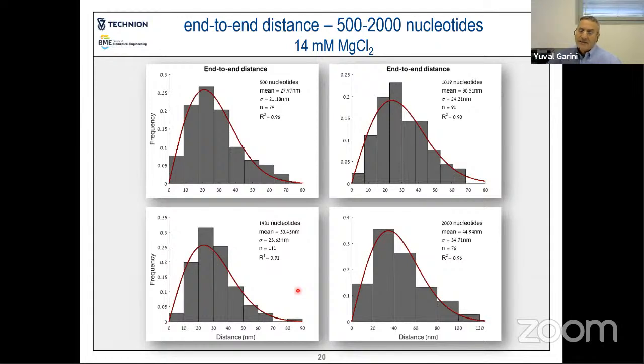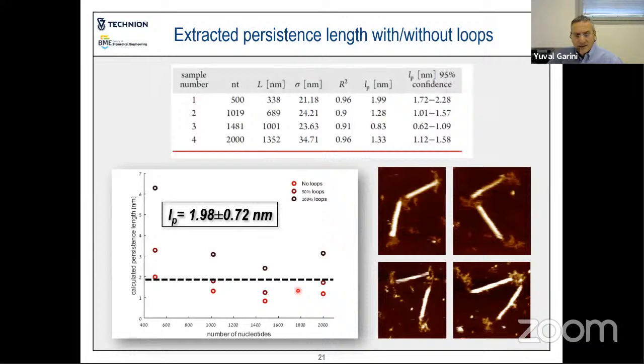We repeated that calculation and fit after assuming that the total number of stem loops is different. And you can see in this summary the results. So you can see for the 1, 2, 3, 4 of the structures, you can see what is the predicted persistence length, assuming that either there are no stem loops in the structure, or that only 50% of the stem loops really exist along the single-stranded DNA polymer, or all of them exist. So of course, according to each of those assumptions, we get a different value for the persistence length, but you can see that it all sums up to something which is, on average, very close to 2 nanometer.